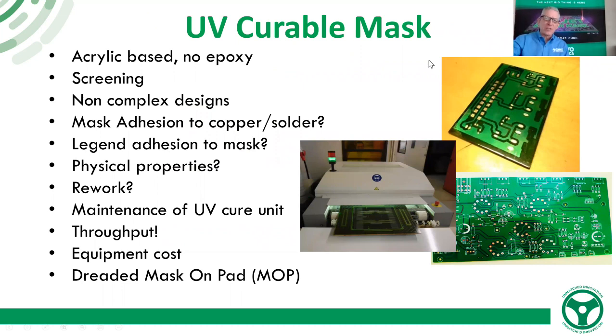So years and years ago, we had what's called UV curable solder mask. And we would take a piece of artwork and we would shoot an image on a screen, and then we'd put the screen over the circuit board, and then we'd use a squeegee to push the ink through the screen onto the circuit board, and then we'd run it through a conveyor through a UV curing oven to cure it. Registration was very difficult. Resolution was not very good. Adhesion of UV solder mask because of the acrylic base was not always the best, but that's what we had.